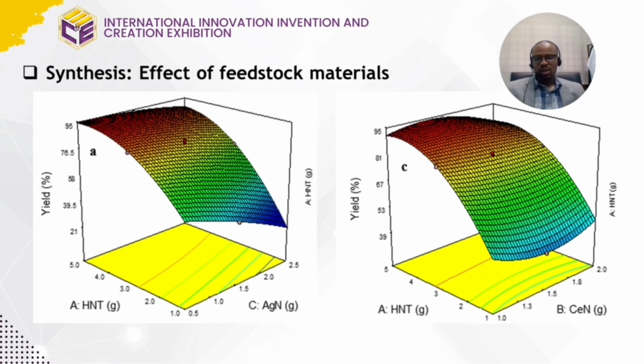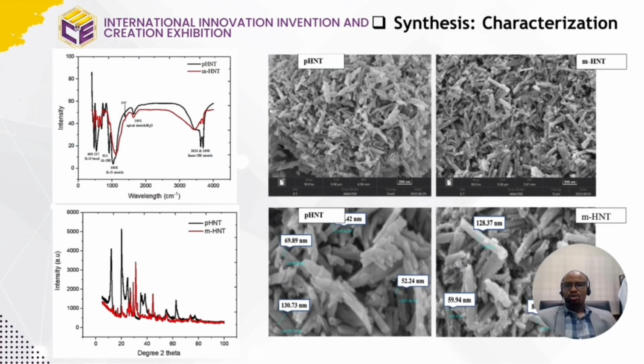So our result shows that there is a significant linear relationship between the input materials and the composite nanomaterials to the yield of the product. As you can see, about 95% of the yield was obtained. So the chemical interactions between the composite materials were investigated using a spectroscopic experiment, and we can see that significant interactions were observed, particularly in the first image.